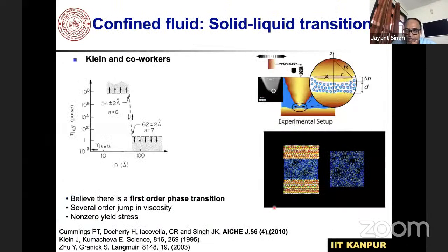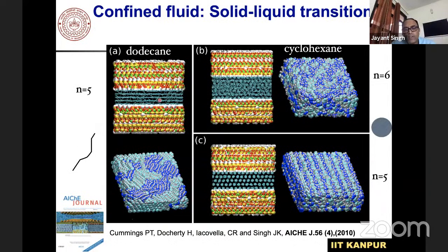Let me see if I can see the movie. It looks like the movie is not playing for some reason. But what we show is that if it is cyclohexane, for example, it is pretty much an FCC lattice. If it is dodecane, it forms a different kind of structure. So we actually calculated the solid-liquid transition for such a system.